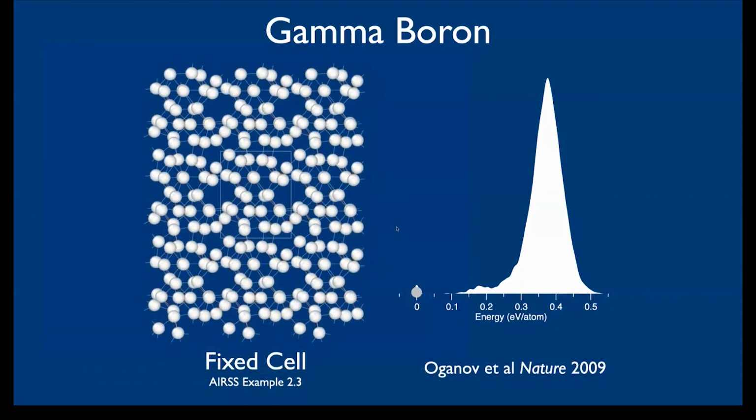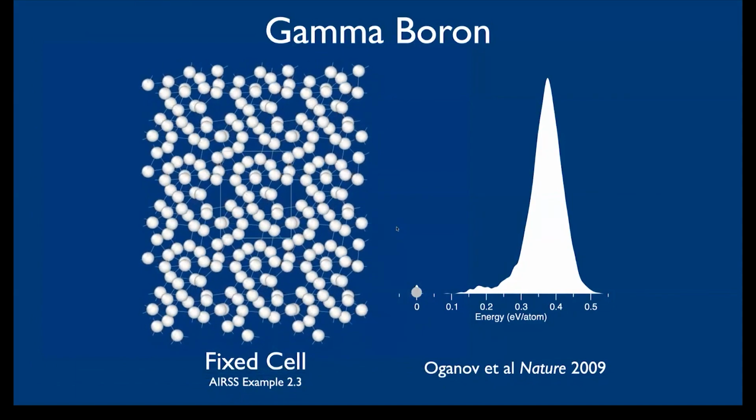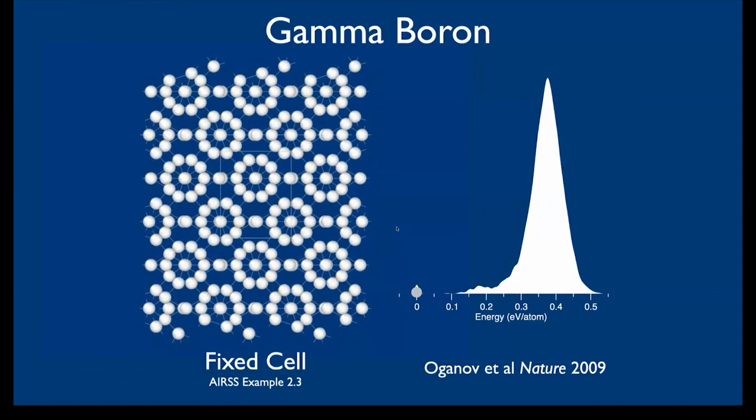So we start from a random arrangement of atoms, we relax, and we go downhill, downhill, downhill, and then eventually it clicks into this beautiful high symmetry configuration. So there was no symmetry applied at the start. It's found the symmetry. But if you only did this calculation once, you'd likely end up in this big peak up here, where the results look quite random.